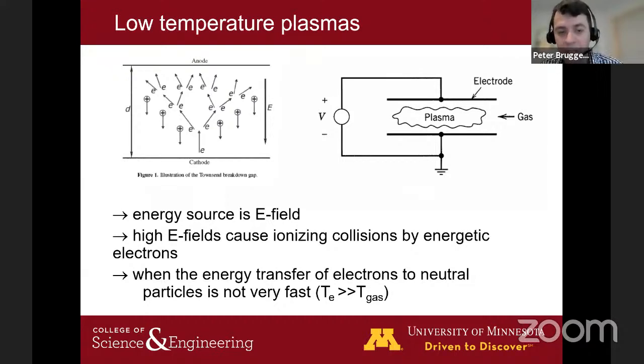The reason for that is that the energy transfer from electron collisions to neutral particles for gas heating, as many of you in the AMO community know, is not as efficient as the energy transfer from an electric field to an electron. That is the key, because this happens on different time scales, so you can create this non-equilibrium. It's the key defining property of low temperature plasmas.